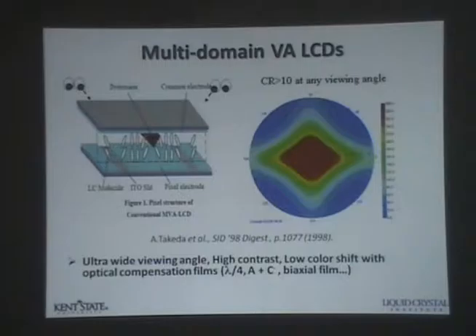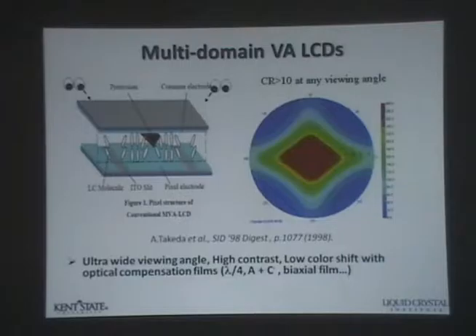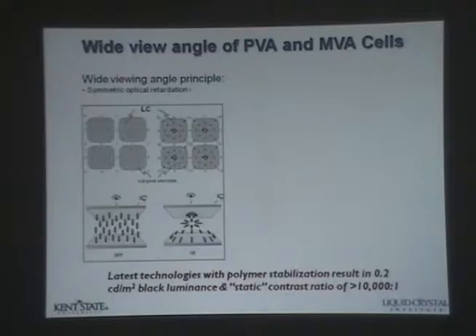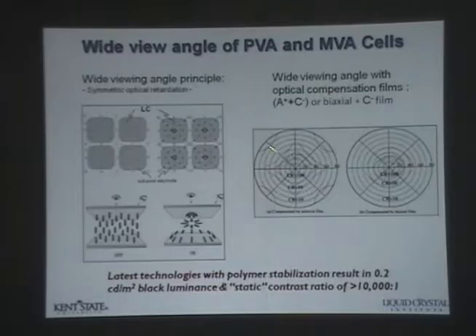What the industry does is use a wide-angle compensation scheme. Normally this uses a birefringent film with negative birefringence that has a minimized optical axis. Using a negative A or positive C film, sometimes negative C, in combination with negative A — various methods to compensate the light image. In some cases, they use a symmetric type of arrangement of liquid crystal alignment to create a wider viewing angle. Sharp uses polymer walls in each single pixel, so the liquid crystal anchors on the surface with a radial distribution of orientation, giving wide viewing angle from all directions.